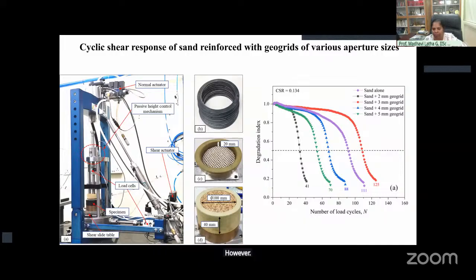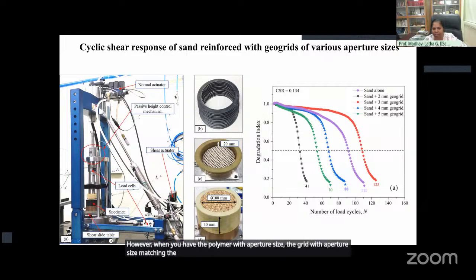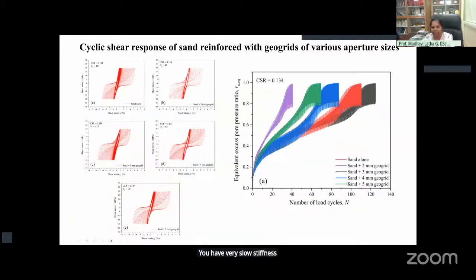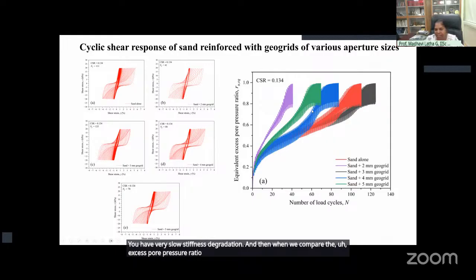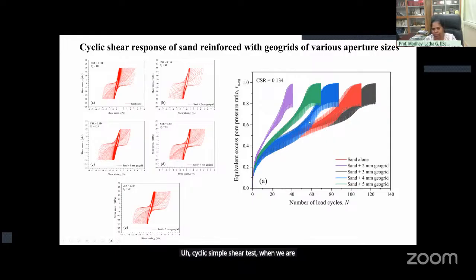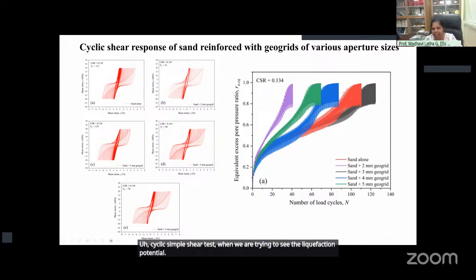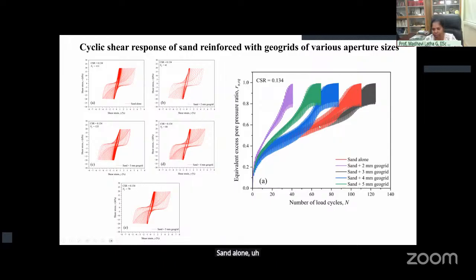However, when you have the polymer grid with aperture size matching the average particle size, you have very slow stiffness degradation. And then when we compare the excess pore pressure ratio generated in the cyclic simple shear test, when we are trying to see the liquefaction potential, the sand alone sample, that is, with no reinforcement, is actually liquefying at about 100 cycles because of the high density of the specimen.